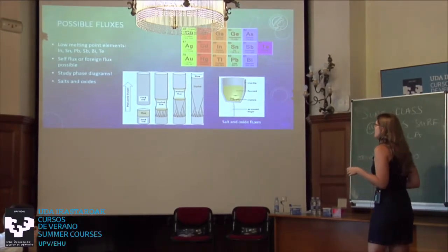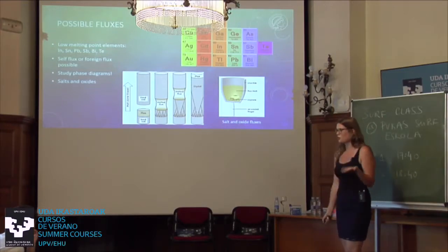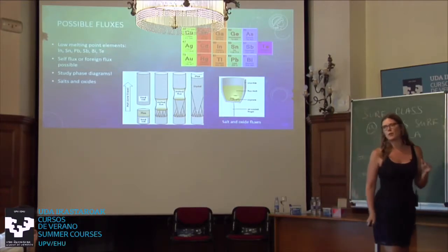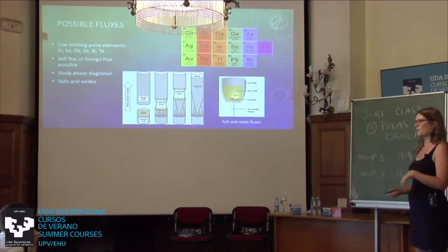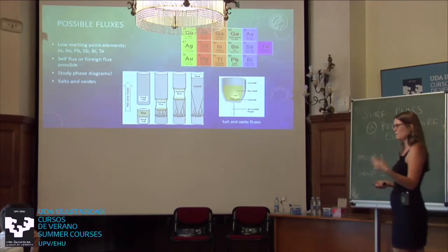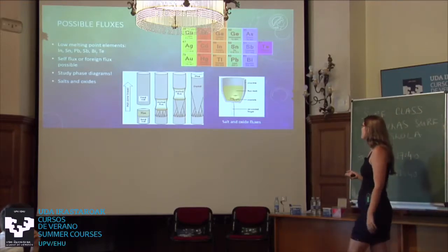However, in order to figure out which flux is good for you to use, you really have to carefully look at all the published phase diagrams between the flux element and the element you're working with and see if they form stable phases or not. So it requires a lot of literature looking to figure it out, and trial and error.